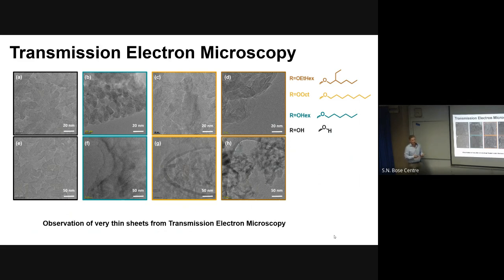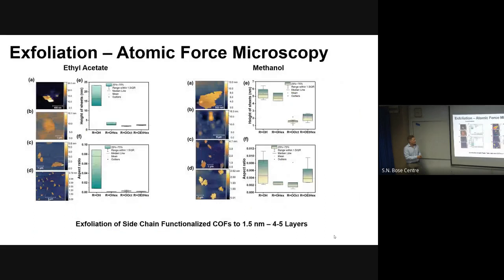Then we moved on further and did some AFM studies. This probably took us the longest time of the study to get these nice AFMs, because we are not from the field really. We needed to figure out how to make the dispersion and how to place it on the right substrate, so we screened a lot of substrates. The next problem is the drying process. If you drop your dispersion on the surface and don't dry it fast enough, the sheets will agglomerate again, and you think nothing happened. You have 100 nanometer high features. This took us nearly 6 months, I would say, to get the perfect conditions to see the size of the nanosheets that we made.